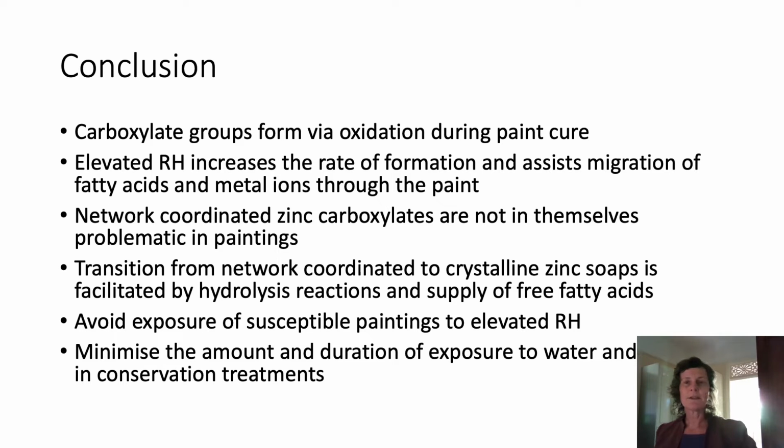Network-coordinated zinc carboxylates are not in themselves problematic in paintings. However, hydrolysis reactions or supply of free fatty acids from additives or other layers within a painting will encourage zinc soaps to crystallize. Prolonged exposure to elevated relative humidity is best avoided, and while the potential impacts of specific treatments on susceptible paintings remains an active area of research, risks can likely be reduced by minimising the amount and duration of water and solvent applied during treatments.